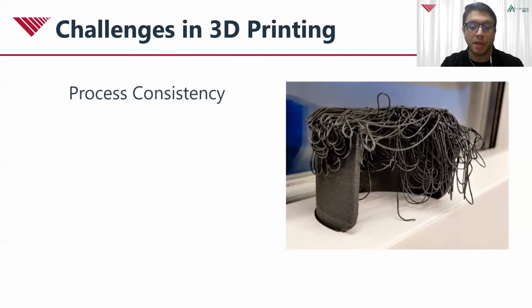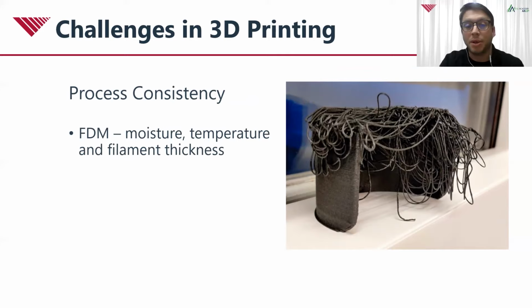One of the biggest challenges with any of the technology is around doing things consistently. All technologies, and especially FDM, are reliant on maintaining a consistent process. Any moisture in the material or in the environment, or deviations in filament thickness can lead to failed prints, such as the image shown here. If the bed isn't heated at the correct temperature, you can also cause problems with the device adhering to the bed and also leading to failed prints. With MJF, this is not specifically an issue, but you do need to be careful about how you align the devices within the print volume. If you pack shapes any closer together than 5 millimeters, you can have issues in those areas.